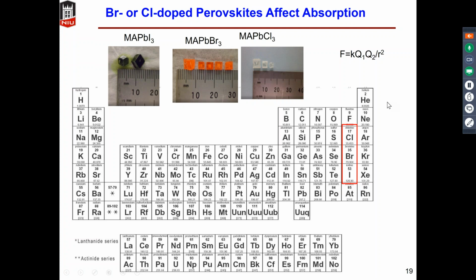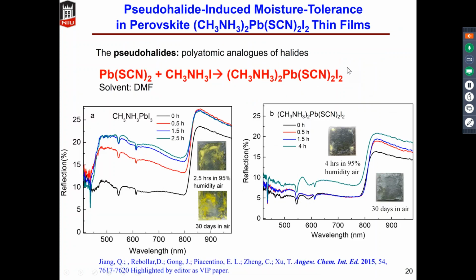So also as chemists, we know that we have some other type of halide, the so-called pseudo halide. So this is our second approach, to try to improve the stability of the perovskite film. We use a pseudo halide such as thiocyanate as the precursor to produce the thiocyanate-based perovskite thin film. And it's quite astonishing that we found that the regular MAPbI3 thin film only lasts actually half an hour in 95% humidity air, or in regular lab air, it just takes a few days to turn into this yellowish film.